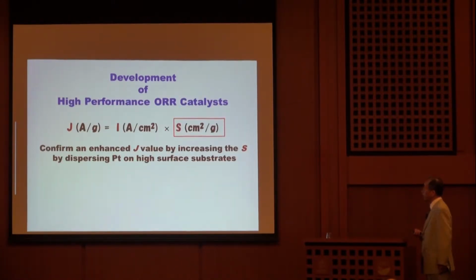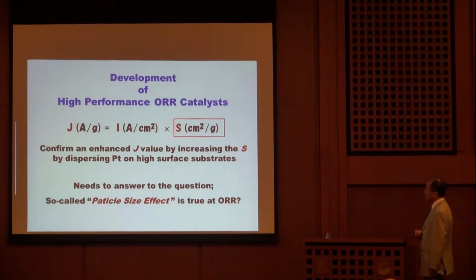First, the development of high performance oxygen catalyst by increasing the specific activity and confirm the enhancement effect by dispersing platinum on high surface substrate. But we need to answer the question, the so-called particle size effect, is true or not for the oxygen reduction.